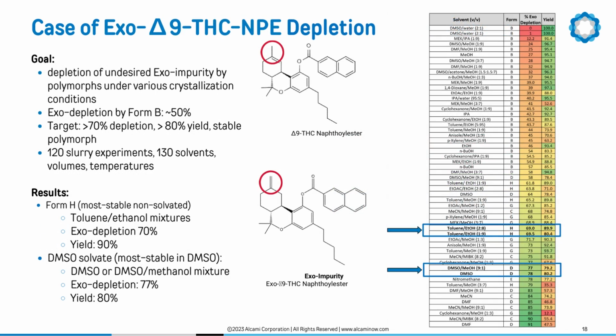In the next phase, the study explored assessment of the depletion of the undesired Exo-impurity by the various polymorphs and under various crystallization conditions. The target was to obtain higher impurity purging level as compared to form B, which was at 50%, ideally above 70%, while maintaining reasonable yields of above 80%, as well as a stable polymorph. The work involved 120 slurry experiments, a range of solvent mixtures, ratios, volumes, and isolation temperatures. The result of the purging study indicated that the depletion was inversely proportional to the yield.